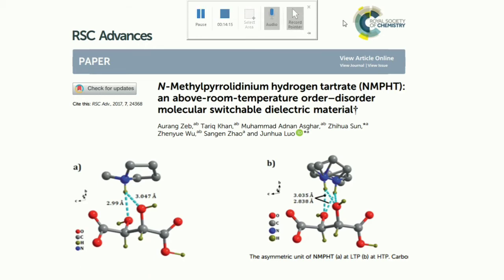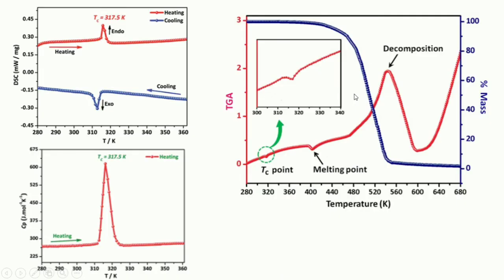In this regard, thermal analysis would help us find the phase transition. If we perform differential scanning calorimetry, DSC, then we can observe that during heating and cooling there is a thermal anomaly. In heating it is at about 317 Kelvin, while in the case of cooling it is at about 314 Kelvin. So there is a difference of about 3 Kelvin between heating and cooling.